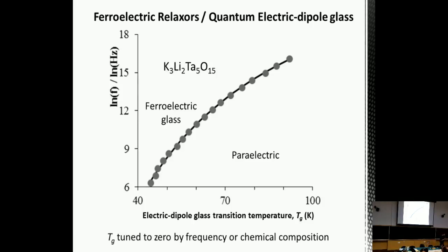And then finally, one more example is a ferroelectric relaxor, which is a bit like an electric dipole glass. And in this example of potassium lithium tantalate, you can actually use pressure and chemical substitution to drive the glass transition temperature precisely to absolute 0. So then this material can be made disorder-free, yes.